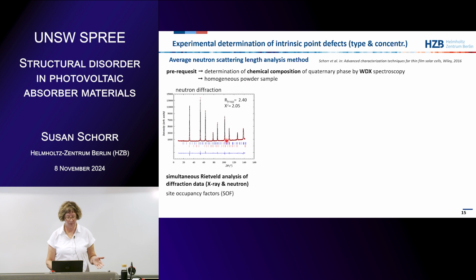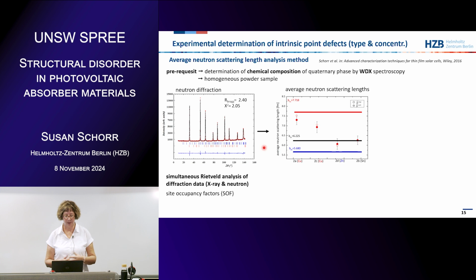So we do the neutron diffraction and the Rietveld refinement. Then we calculate this experimental average neutron scattering length. These are the points here. And this is for each of the 4 sites, so 2A, 2C, 2D, 2B. And then we compare this with the neutron scattering length of the element. So the red line is for copper, the blue line for zinc, and the black for tin.